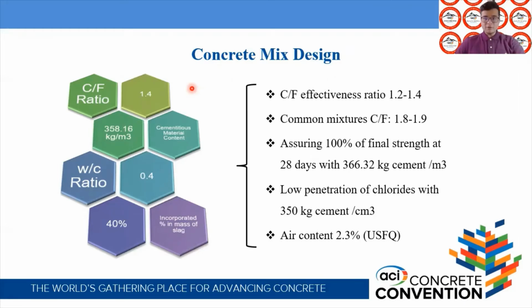The cement content was obtained by averaging the results from one research stating that the best performance was with mixtures containing 350 kilograms of cement per cubic meter, and another having samples with an average of 366 kilograms per cubic meter, that reached 100% of the expected final strength at an age of 28 days. The water-cement ratio was set in the competition rules, while the proposed air content was obtained by averaging the results from graduate theses and laboratory reports from students at the university.